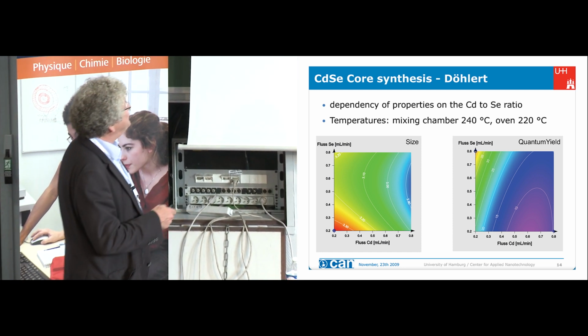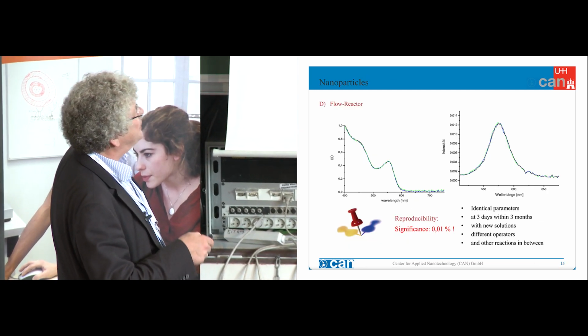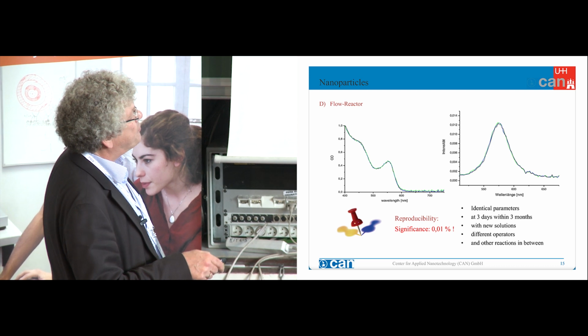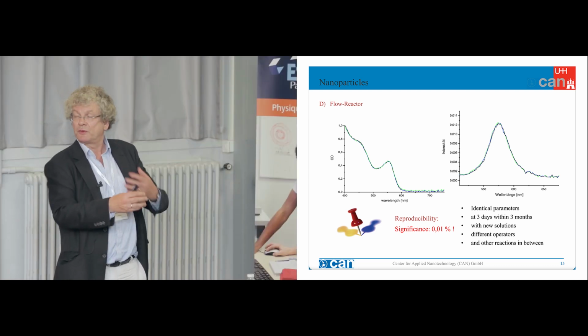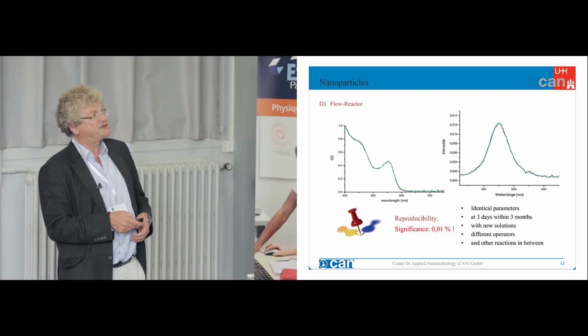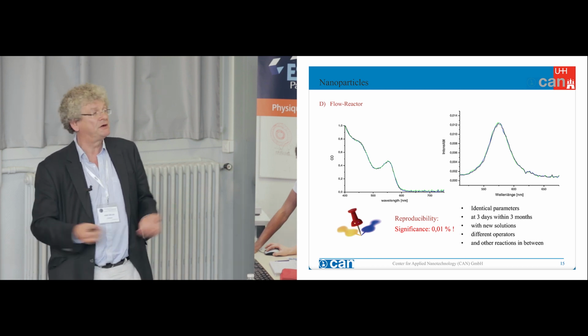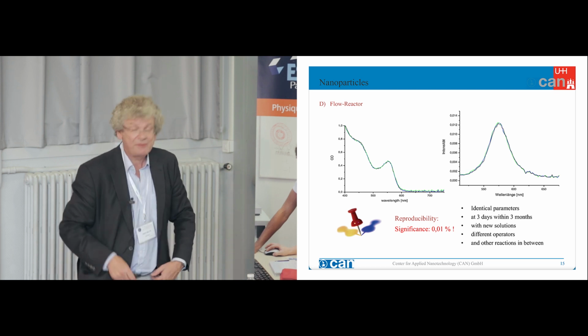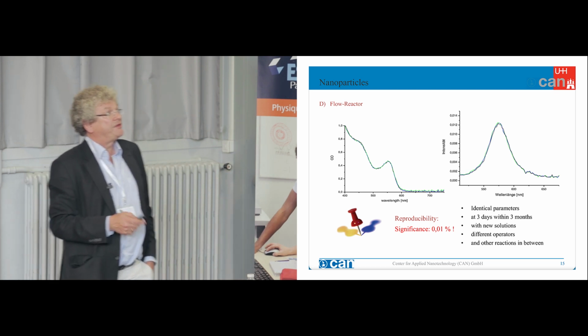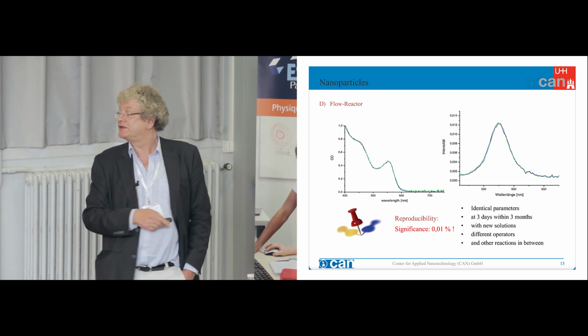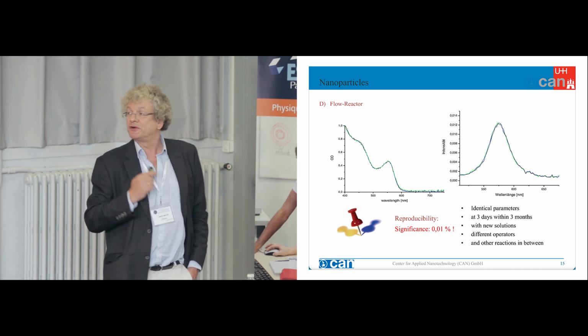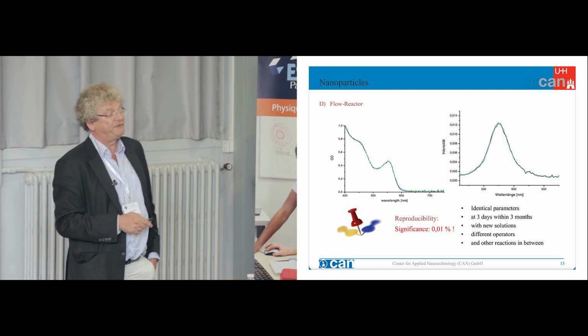And this you can see here very nicely. So 3 samples here made within 3 months at 3 days, but not one day after the other. Some reactions in between, different reactions in between, different operators, which make, of course, no difference. It's just typing in the parameters in the computer, but exactly the same. So this is really reproducible, and it works very nice.